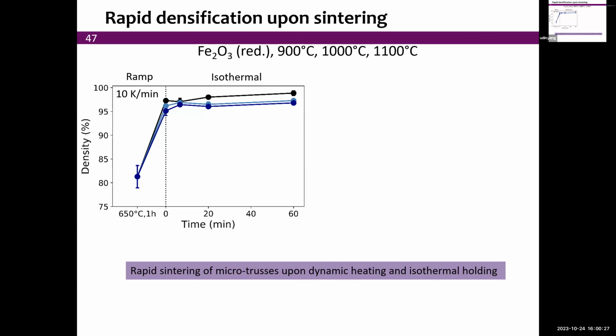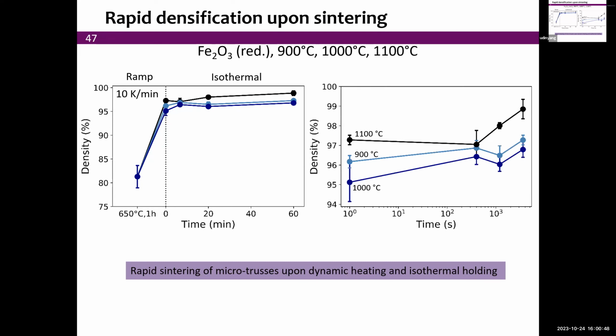All right, so if we now go from the pre-sintering to the maximum temperature of either 900, 1,000 degrees or 1,100 degrees C, which is our final sintering, and then we hold. We hold for about an hour. We see the density jumps from about 80%, what we just saw a minute ago, to about 98 to 99% sintering. And if we zoom in here, we see something a bit unexpected.